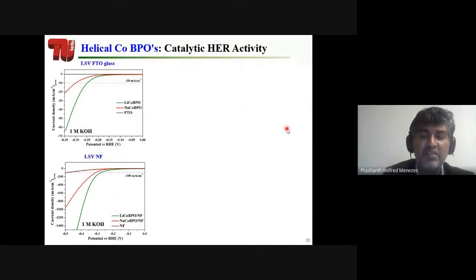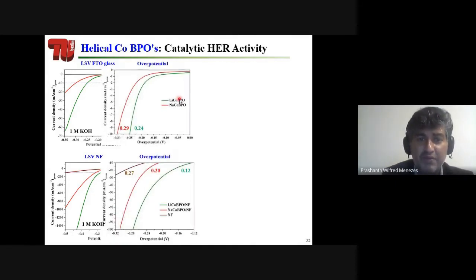Now, once we know that this system works for oxygen evolution reaction, we try to check it for hydrogen evolution reaction as well. This is the linear sweep voltammetry curve for hydrogen evolution reaction. Zero is the thermodynamic potential. The extra potential what we put is overpotential, and this is on FTO glass, and this is on nickel foam. What we see, we have almost 240 millivolt of overpotential. This is very low compared to other systems. And if you use nickel foam, we have only 120 millivolt of overpotential. That means 120 millivolt of extra potential we require to reduce water.